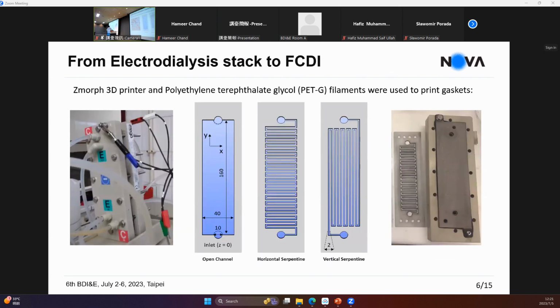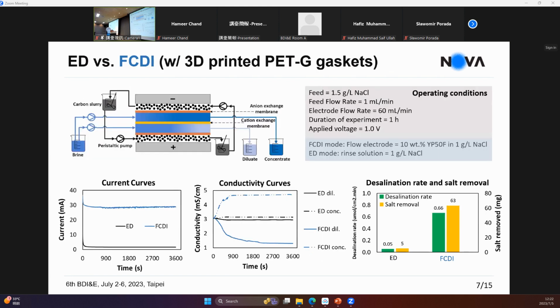And what we did, we had in our lab some electrodialysis stacks. So we used the end plates from those electrodialysis stacks, which have these titanium platinized electrodes, which we use as current collectors. And we printed several different gaskets using the 3D printer and PETG filaments. So these are a non-conductive material. So we printed those gaskets. In the end, we always use this serpentine horizontal arrangement, and we compared the performance of electrodialysis with FCDI with those 3D printed PETG gaskets.